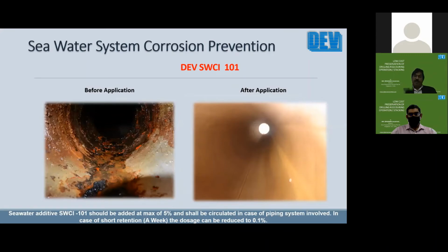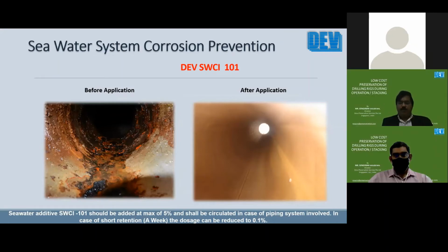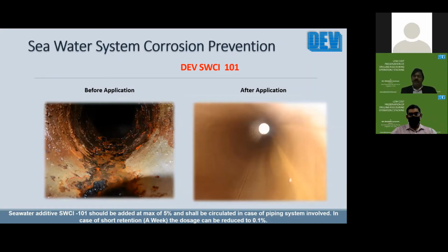When coming to seawater corrosion, this is a major problem area for our clients, wherein the seawater piping tends to be repaired after 4 to 5 years of operation. And this we are able to completely eliminate with this additive, SWCI 101. This additive is able to bring down, as I said earlier, the rate of corrosion to 0.013 mm per year. As a result, the corrosion allowance that is provided is more than adequate. Even at the time of the asset getting scrapped, the pipe will have adequate thickness. So you will never have to repair or replace.